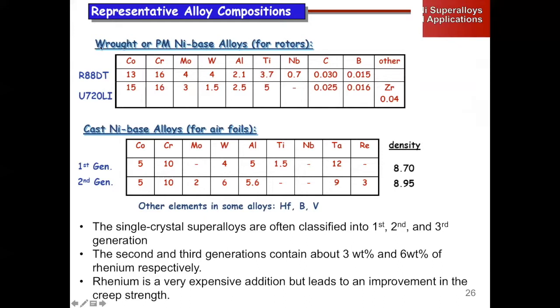The main difference between rotors and airfoils is airfoils need to be single crystal, right? They're going to have a smaller fraction of cobalt and chrome, a higher percentage of tungsten and aluminum, right? We're going to increase our gamma prime forming elements, to try and get our gamma prime fractions as high as possible, right?